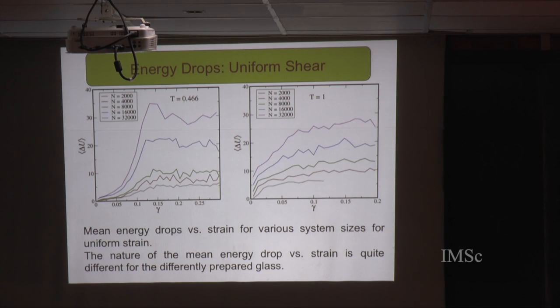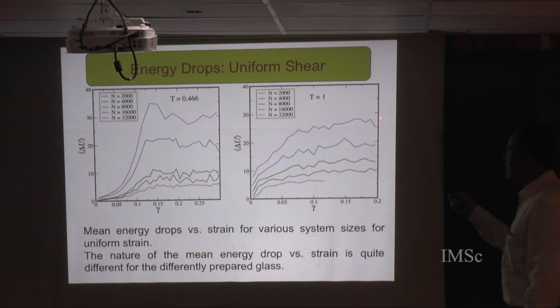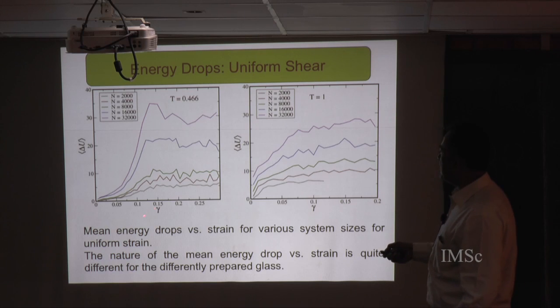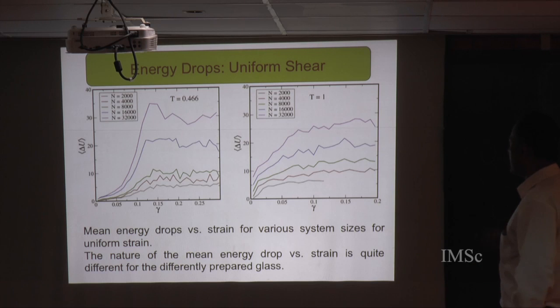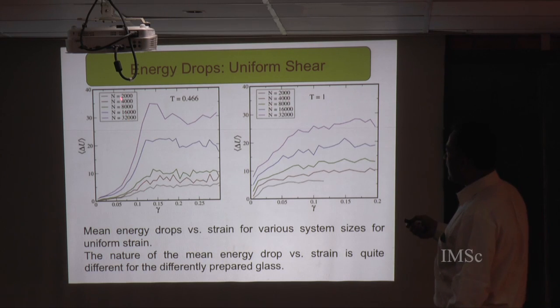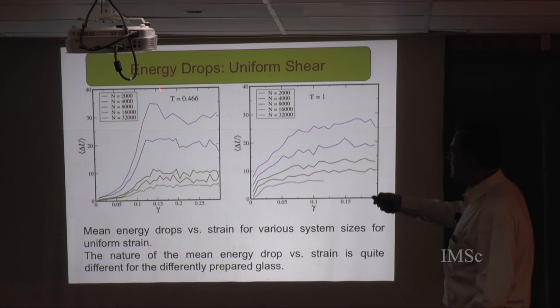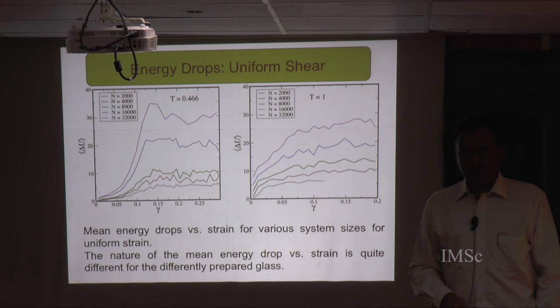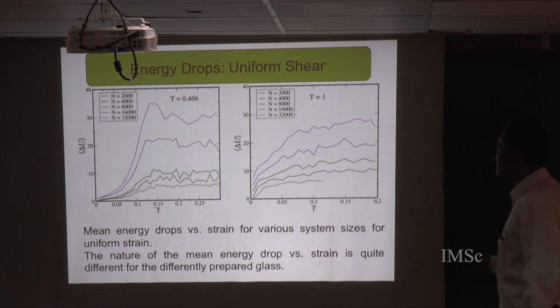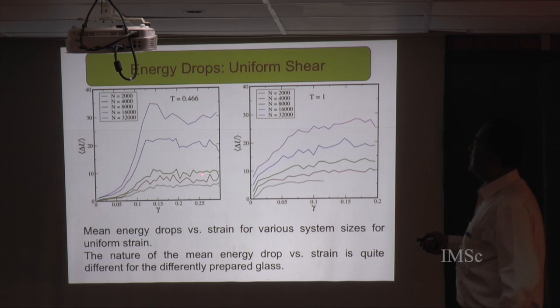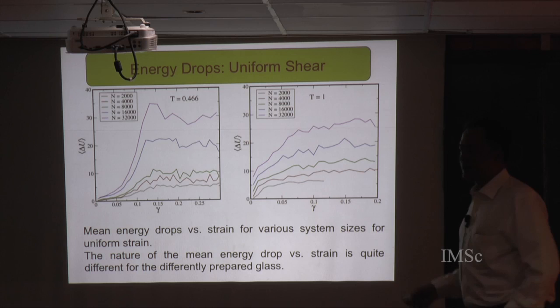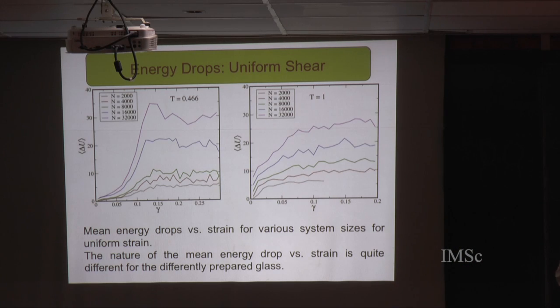If you look at these energy drops in the case of uniform shear as a function of strain, you see two points: as a function of system size, the size of these drops is getting bigger and bigger, and if I look at the well-annealed glass versus the poorly annealed glass, the behavior looks very different.